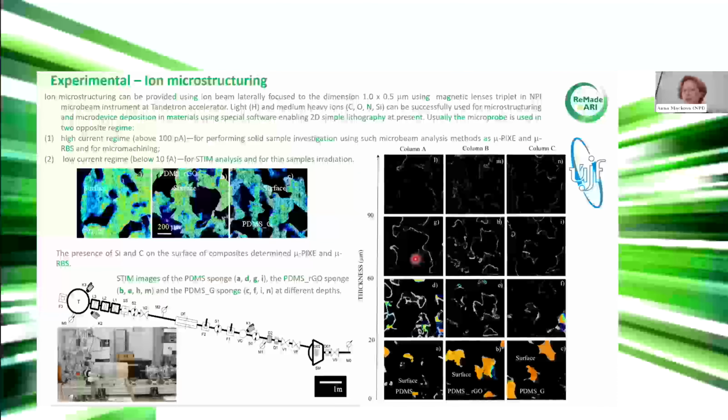So we had samples implanted only with gold and then with a combination of gold and silver, when we kept the silver fluence the same and increased the fluence of gold. And after the implantation, we employed RBS again, because RBS gives us a very nice spectrum, where we are using helium ions with 5 MeV, and we saw gold signal, silver signal, and zinc signal.